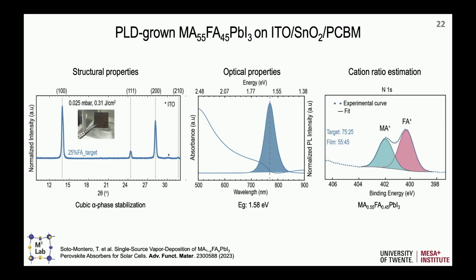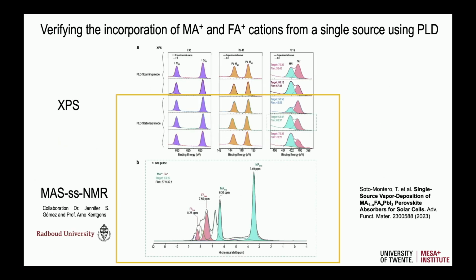And then we can also do XPS to estimate the cation ratio. So in here are the nitrogen core levels that are very different for MA and FA, so you can quantify or at least estimate how much you have on the surface. So now we could confirm that we have this, based on the target that we use. But of course, XPS is a surface technique. So we needed basically NMR to see what is in the bulk and to confirm that we are not killing the FA molecules because they degrade very easily, as we know for co-evaporation.